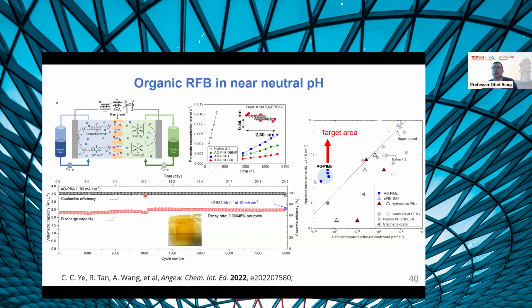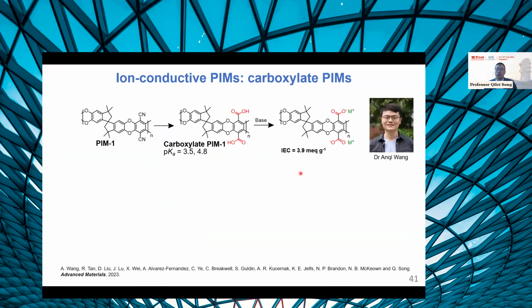You can see that by pairing these AOPIM membranes with the modified quinone molecules, we were able to achieve stable performance over 1 month. But the challenge is these PIM polymers are really selective. You can see that the diffusion coefficient of these redox species is really low, but the conductivity was not very high. So that limits the energy efficiency of these batteries. So we realized, especially if we want to achieve high energy efficiency in the neutral pH flow batteries, we need to develop some other functional group.